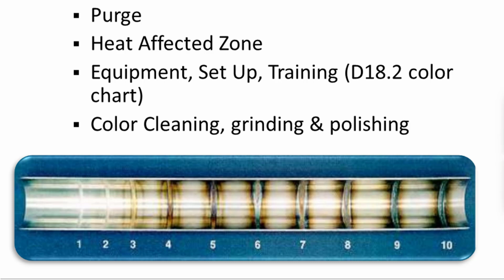This has been done with the machine, has the same setup, but the only thing that was changed was the parts per million of oxygen. So this is shown to show you that your oxygen content at very small levels will affect the coloration because it's oxidizing. But if I took this number 3 weld and I increased the amperage on that welder to try and make it go faster, or I slowed the speed down so it actually had higher dwell time, that same oxygen content might look like this.